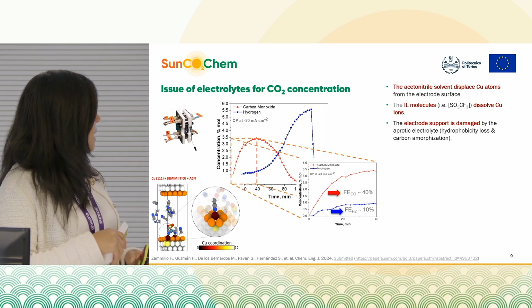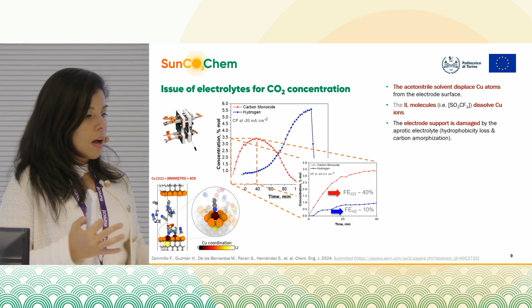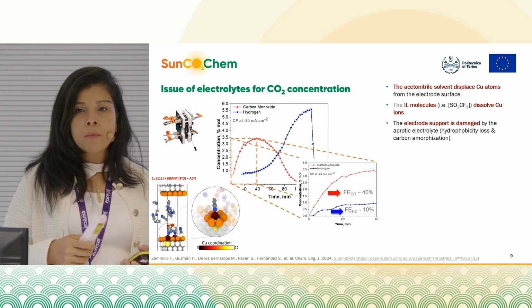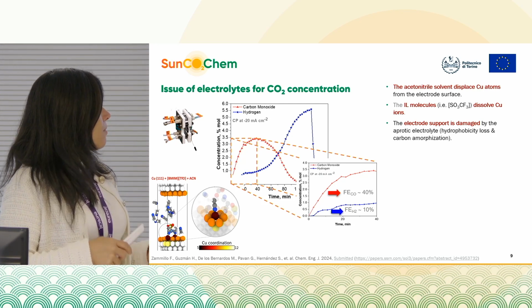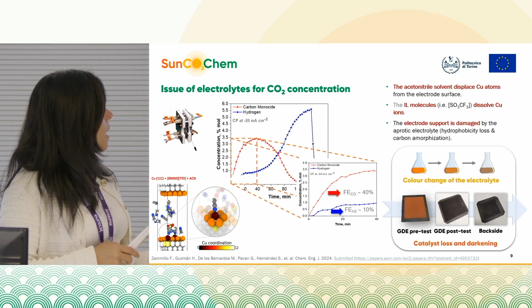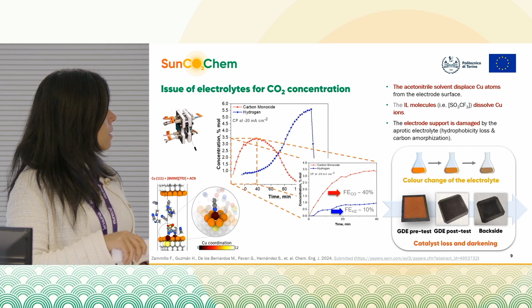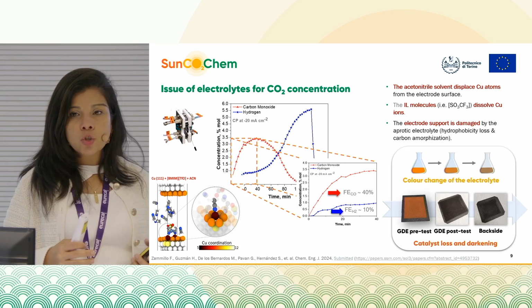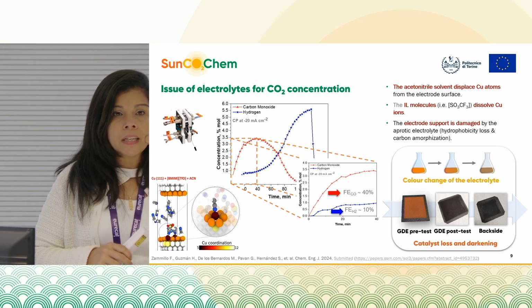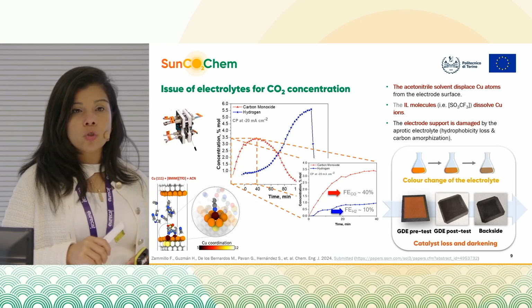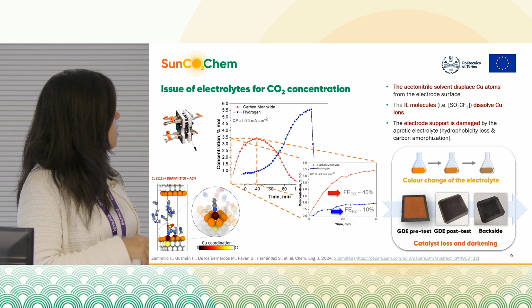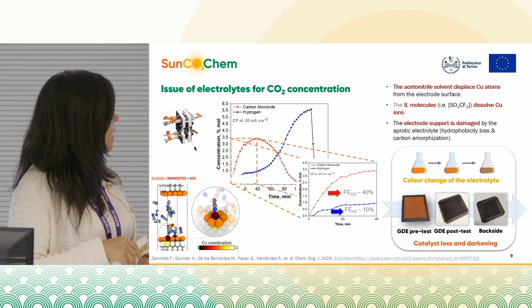And other than that, the exposure of the carbon-based support also affected this gas diffusion layer, damaging the support and creating some amorphization of the carbon material and some hydrophobicity loss of the electrode. So these were the reasons for this instability of the material.